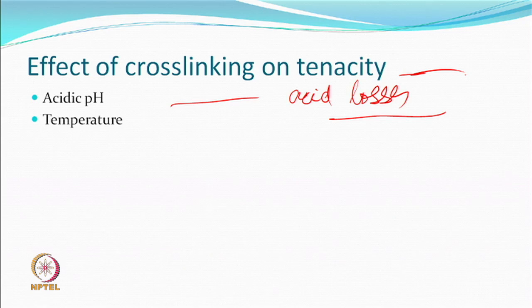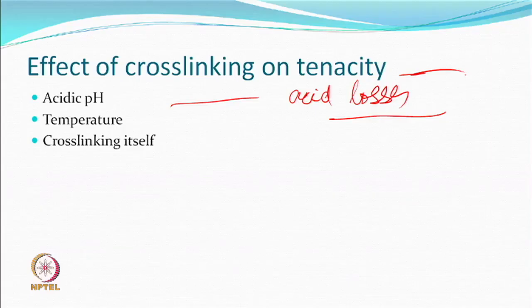Then temperature, we are saying curing temperature is going to be high. So because of acid plus temperature, again the loss can take place. At room temperature, the difference will be different, and at higher temperature, it is different. You see, what happens is when you dry, whatever concentration of acid that you have taken in the beginning on the fabric, as the water goes out, the concentration of acid keeps increasing. So acids can become concentrated on the substrate. But if they become concentrated only at the time when cross-linking is required, then they are participating in the reaction. If it happens before, then the loss can occur. For example, if you don't use a cross-linking agent, just have acid and temperature, you will get higher loss than when you have a cross-linking agent. The cross-linking itself is supposed to bring some loss, but that depends on which fiber you are talking about.